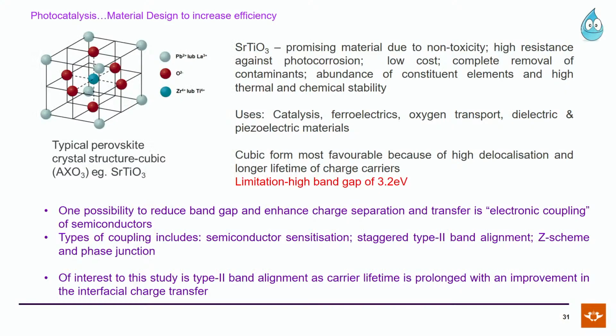So one way to do this is through electronic coupling of semiconductors. The different methods of this electronic coupling include semiconductor sensitization, staggered type 2 band alignment, Z-scheme, and phase junction. Of interest to this study of ours was the type 2 band alignment. Why? Because carrier lifetime is prolonged with an improvement in the interfacial charge transfer.